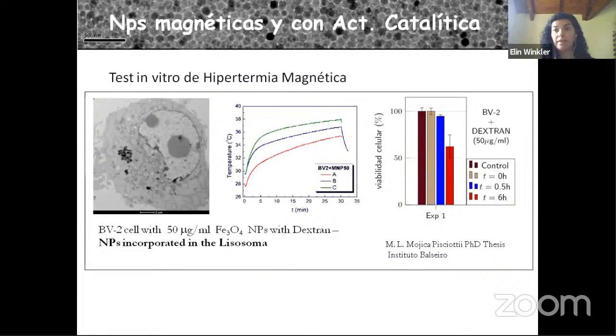we have worked in magnetic hyperthermia for many years, and Maria Luz Mojica Picciotti made a PhD under the supervision of Roberto Zysler, and they internalized the nanoparticles into the cells. This is a cell, and the black spots correspond to nanoparticles, and then they applied AC magnetic fields. They made hyperthermia experiments, and they measured before and after the hyperthermia.